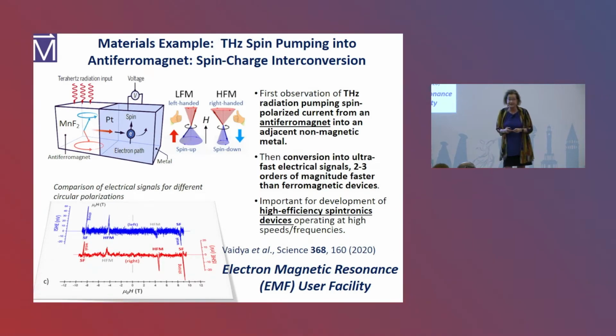This one I'm glad I threw in here because Ahmet might be interested in it. So this is all still prototype. This is some of the spin transport they were doing in our electron magnetic resonance area. So this is EMR. They also call it electron paramagnetic resonance, depending on where you've been. But what we have here is an antiferromagnet that's attached to a non-magnet, okay? So this is a heavy metal, platinum, manganese difluoride, and you send in terahertz radiation, and you get a spin transport across, and you can bring out ultra-fast electrical signals. So it's spin transport through this platinum.